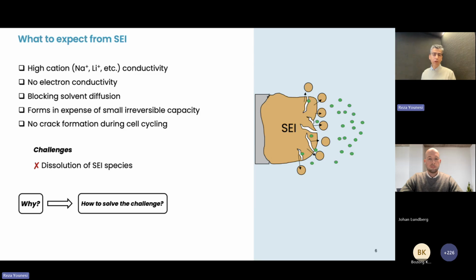So the first topic to cover is the solid electrolyte interphase, or SEI, which probably most of you know is a very critical component in the cell to make the cell kinetically stable. The reason is that the electrochemical potential of the negative electrode is beyond the stability of the electrolytes. So we need to make this thermodynamically unstable system somehow kinetically stable, and that is done by forming SEI. You probably know there are a few requirements for SEI, like ion diffusion, etc. But one thing which is a little bit neglected in the literature is the chemical stability and dissolution of SEI.